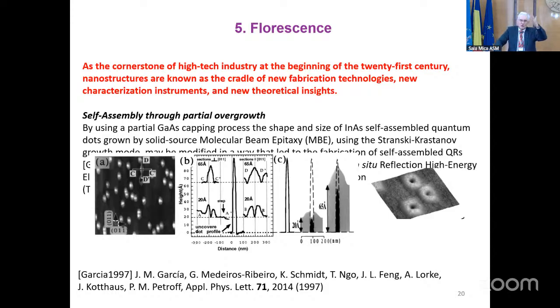But just at the edge of the new millennium, this paper by Garcia and others showed that you may grow indium arsenide quantum dots by solid source molecular beam epitaxy within the Stranski-Krastanov growth mode. And after the growth of dots, some islands, some singly connected objects, they were covered with some additional layer. It can be GaAs, for example, and annealed after some time.